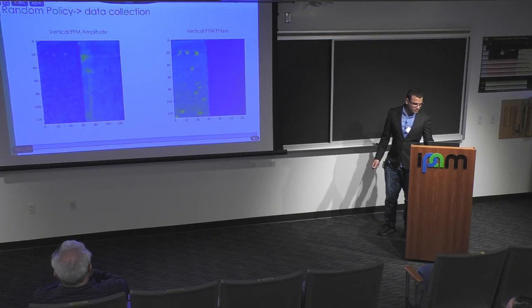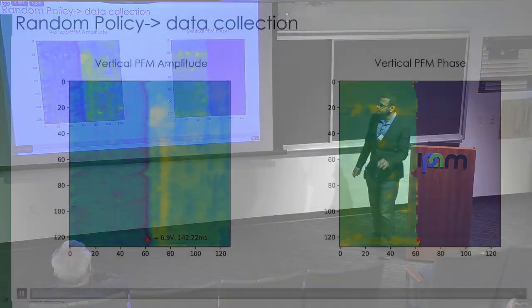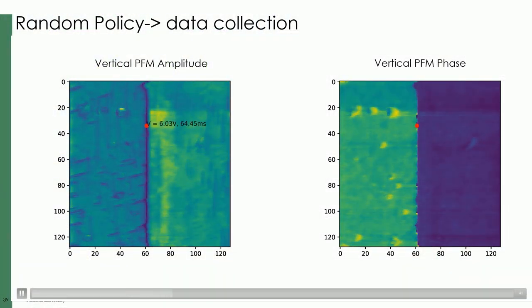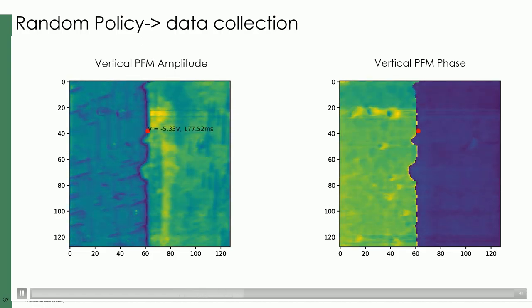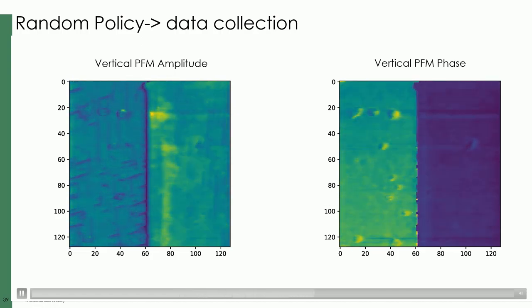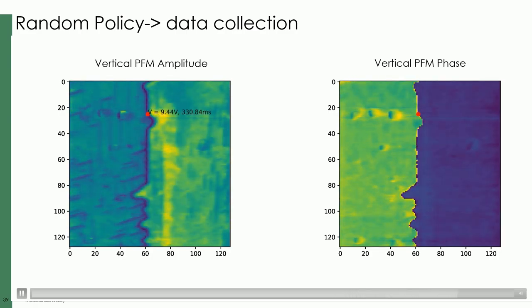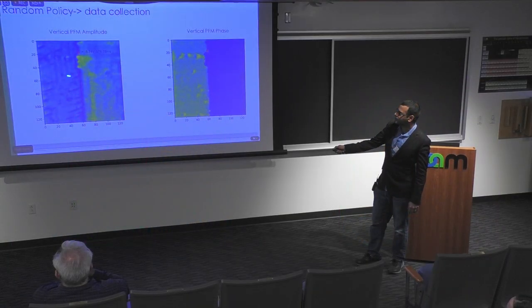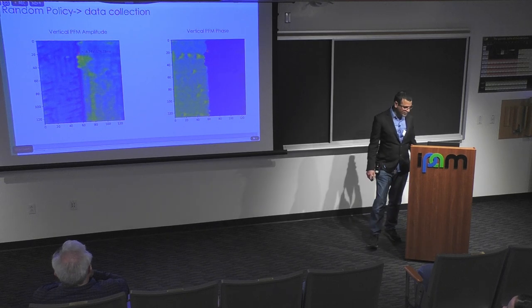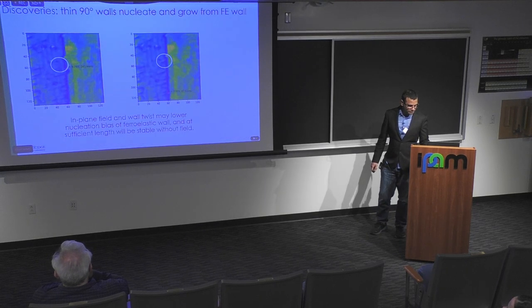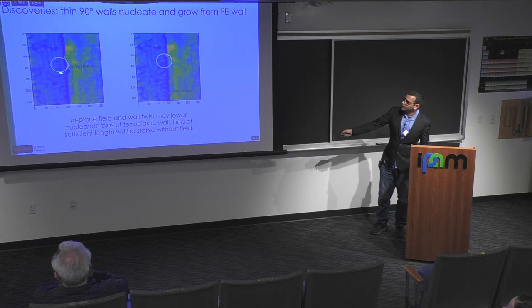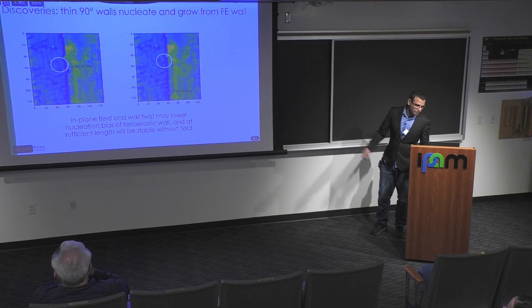We can also do this. This is just another example of the same kind of experiment. I call this the machine gun video because it's like we are applying a lot of pulses in a very short amount of time. Of course, this is not a short time. This is actually 2 days, but it's sped up for you. So you can see some very interesting phenomena that occur when we do this sort of experiment where, for example, repeated pulses will actually grow some needle domains from the center, which is probably related to lower nucleation energies. You see that here, for example, there was no needle domain here, and after enough pulses, it started to nucleate and grow from here.